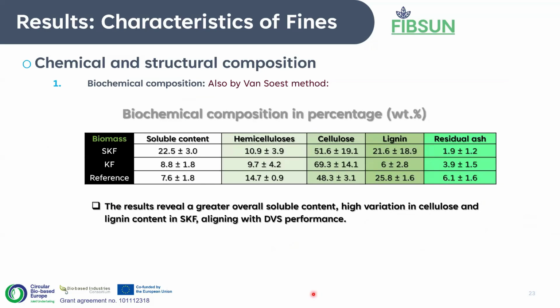What we did then is to understand why, more often than not, chemical composition plays an impact in terms of these kinds of properties. And so we found that SKF, which is a super short hemp fiber, has a substantially high soluble content and high variation in lignin content, and this is because the material comes more from the core, which is always the lignin-rich section of the stalk. In comparison to the reference, we see that the low absorption rate of KF has implications with the hemicellulose content, because the hemicelluloses of wood and of hemp are not directly comparable in terms of the specific type of sugars in this lignocellulosic material. However, we still see that in the case of wood, the high hemicellulose content could have played a part in why the absorption rate is slightly higher compared to KF.